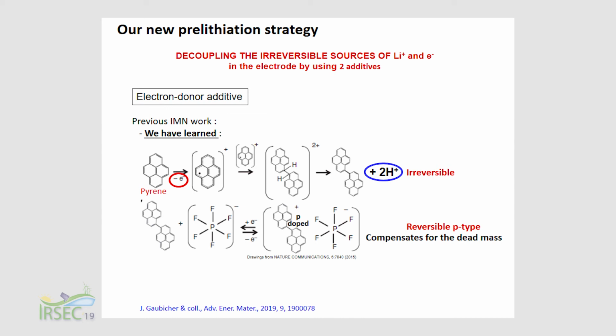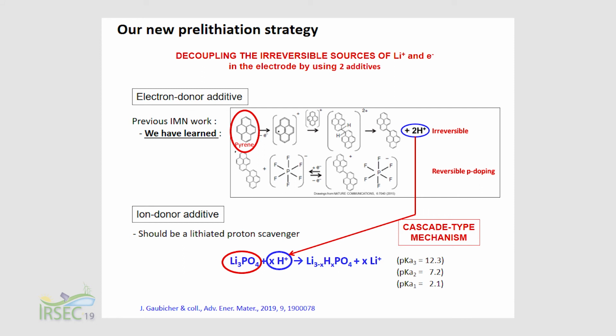But you can see that the first irreversible electropolymerization of pyrene releases some protons. So this can be a problem. And we took advantage of this proton release to design a lithium-ion donor additive, which is a proton scavenger. And the easier, the better.